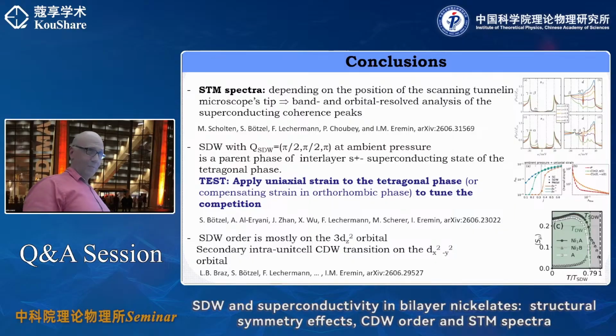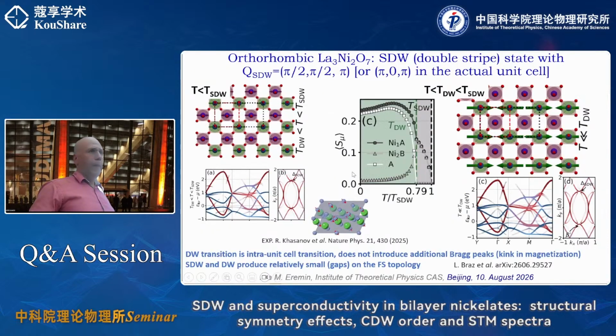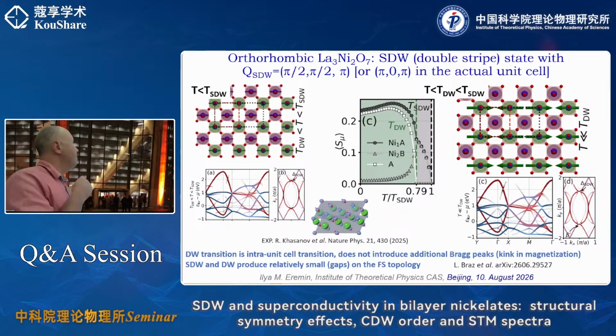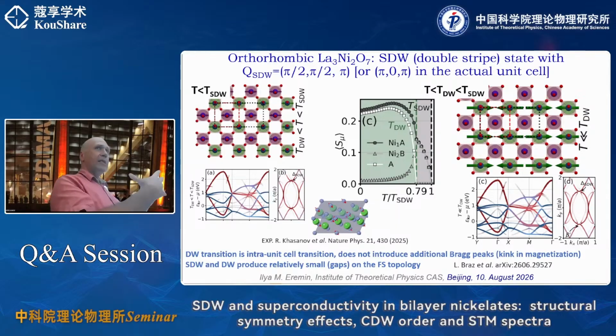The question for the last part, when you mentioned the charge density wave and the spin density wave. As I heard you mention, in your calculation you already set some kind of charge density wave in to do the calculation. No, for this case, no. In this case, we just allowed... because when you do the Hartree-Fock, of course, you essentially need to allow certain initial orders. Right. But apparently we don't have an instability.